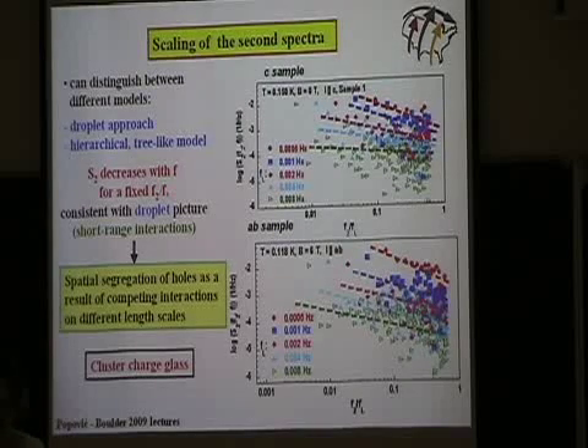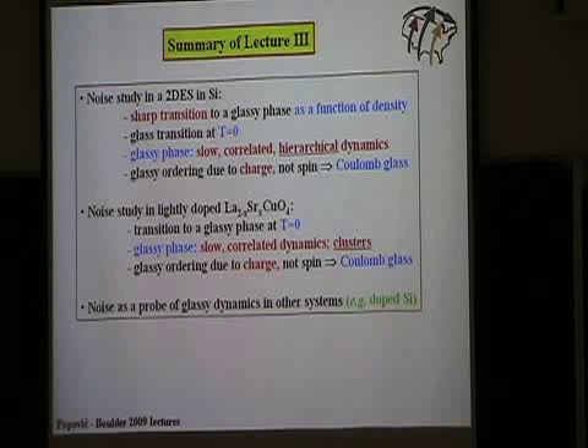So things are different, and I'm running out of time, but basically, what I showed you today is that noise can give us very useful information. We can use it to identify the glass transition. So we found glass transition as a function of density. It also helps us differentiate between different theoretical models. In the case of a pure Coulomb glass, with no magnetic degrees of freedom, we found that this fits the hierarchical models of glassy dynamics. On the other hand, in these lightly doped cuprates, we also found evidence for the formation of a Coulomb glass, but this is a cluster charge glass because of the presence of other interactions in the system.